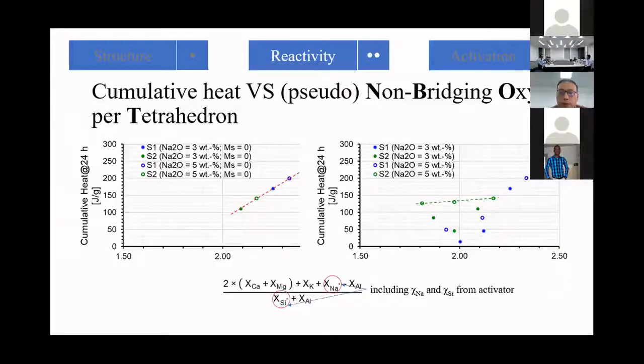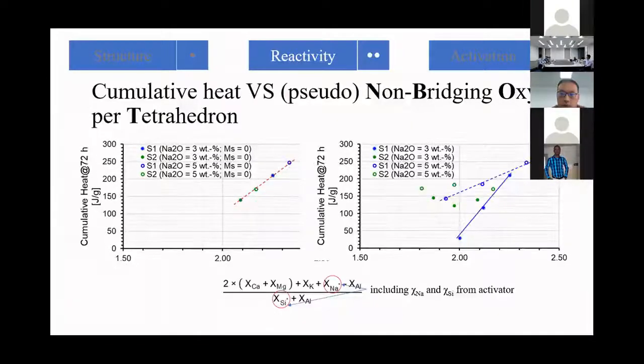Unfortunately, in the presence of the silicate, the correlation is not so good. It means that in the presence of the silicate, the reactivity of this SCM is not only controlled by the dissolution of the glass, but also by the reaction products, which impede or influence the reaction of the SCMs.